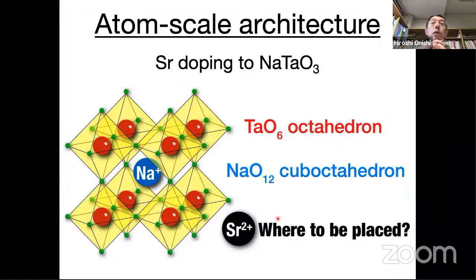discuss this, we wanted to know the precise chemical structure of our photocatalyst, more specifically, where strontium cations are placed in the host crystals. Sodium tantalate has a perovskite type structure. The large sodium cations are the blue spheres, the small tantalum cations are presented as red spheres, and the blue green balls are oxygen anions. So this is a typical perovskite structured lattice. And now we put a small amount, 1% or 2%, of strontium cations into this lattice.